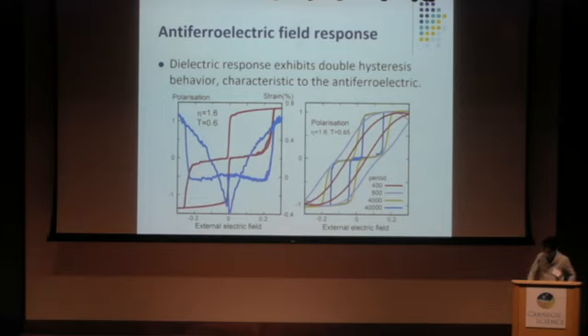Because our model particle is anisotropic, like a spheroid, the transformation induces very large strain, shown in the blue line. And maybe an interesting result is in the right panel, the frequency dependence of the response. For lower frequencies, the blue line is the antiferroelectric double hysteresis response, but for higher frequencies, there is not enough time to transform from the ferroelectric to the antiferroelectric phase, and the response exhibits a single hysteresis curve, characteristic of the ferroelectric phase.